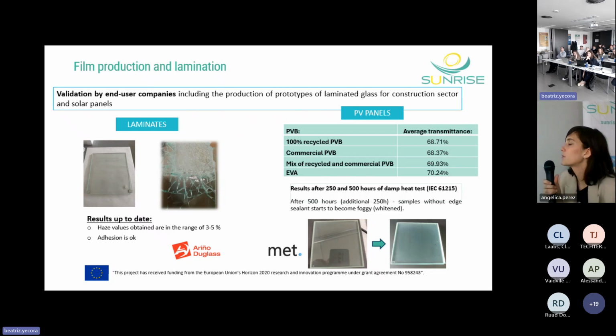So in terms of these laminates produced by Ariño, we still have to improve our optical clarity, because we are obtaining haze values between 3-5%, considering we are mixing with virgin PVB. So still we need to improve this. We are going to work in these 6 months, try to make modifications to improve a little bit more, to see where is our limit. And then what we have already achieved when we mix with virgin PVB is the adhesion and the mechanical properties, that these are okay. This is the Pummel test, made by Ariño with some of the samples of the project.